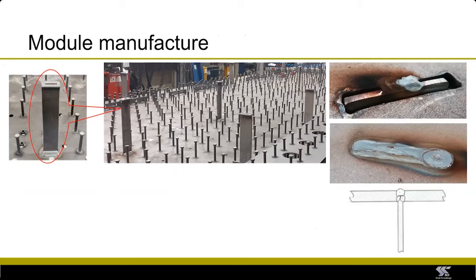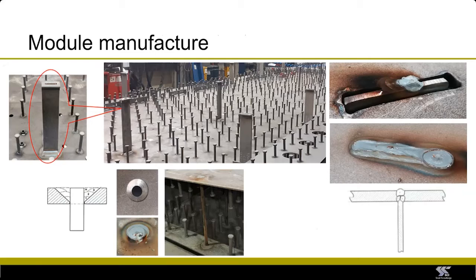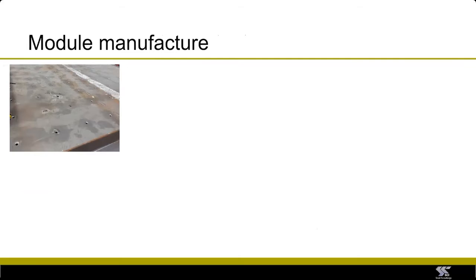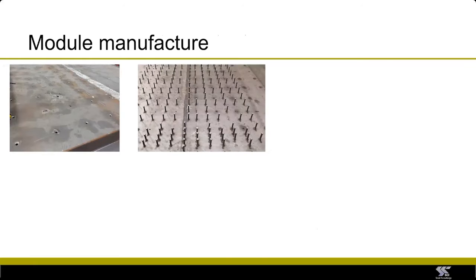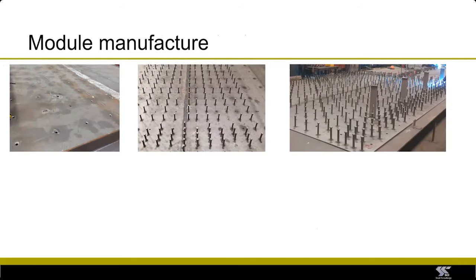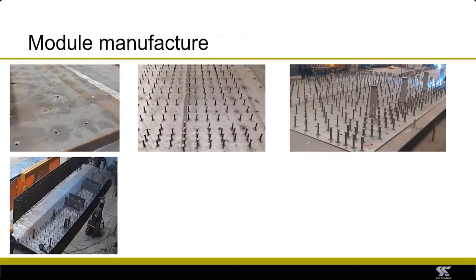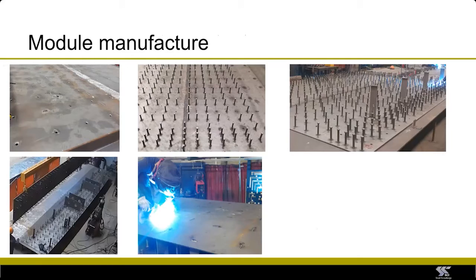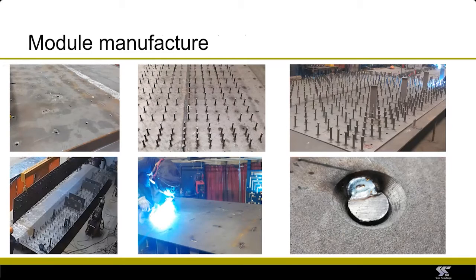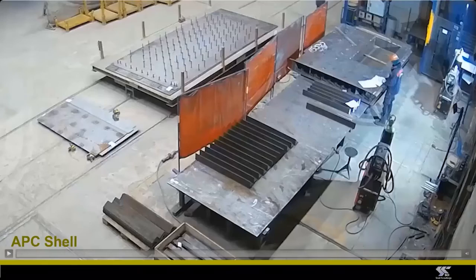Once the second plate is placed on top of the stiffeners, it's then welded. The stiffeners are welded from the outside to the plate, and then the bars are inserted and welded from the outside to both plates. So the sequence is we cut the holes in the plates for the bars, we weld the shear studs on, we weld the short stiffeners on, then we bring the second plate with the studs welded to it and place it on top of the stiffeners, and then we weld from the outside the second plate to the stiffeners, and then finally we insert the tie bars and weld them from the outside to both plates.